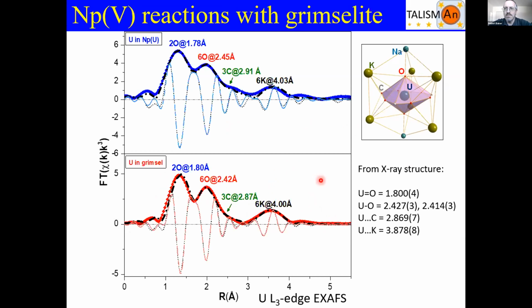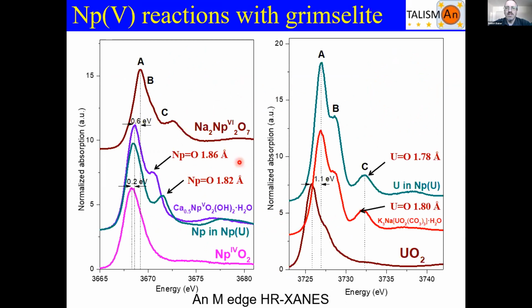We turned out to be quite lucky because this is neptunium rich. So we can see the neptunium edges quite clearly and the uranium edges as a smaller feature. But we can't tell whether these are mixed or phase separated. So these are the M-edge XANES spectra.